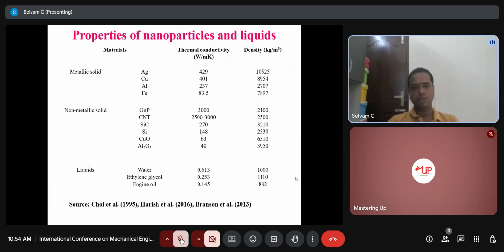In order to maintain the stability of the nanofluid, the density is very important. At the same time, to increase the thermal conductivity of the nanofluid, the thermal conductivity value is also important. Even if the thermal conductivity value is very high, but the density is also very high, that won't be significant, because it will increase the thermal conductivity but the stability of the nanofluid will be greatly reduced. So we have to focus on both thermal conductivity as well as density. In the metallic solids, silver and copper have high thermal conductivity, more than 400 watt per meter Kelvin. At the same time, the density is higher.